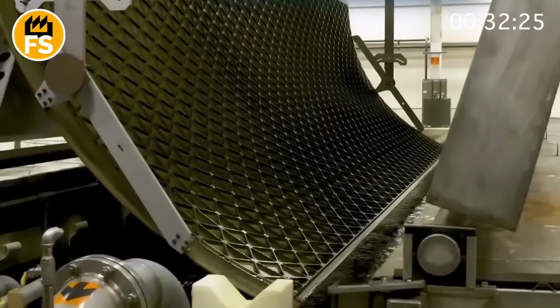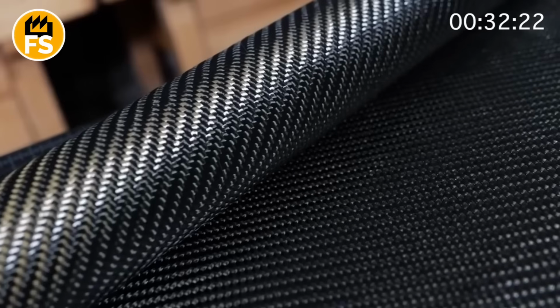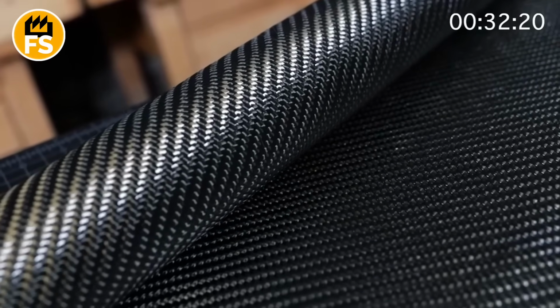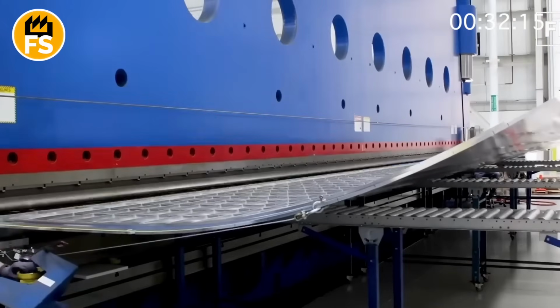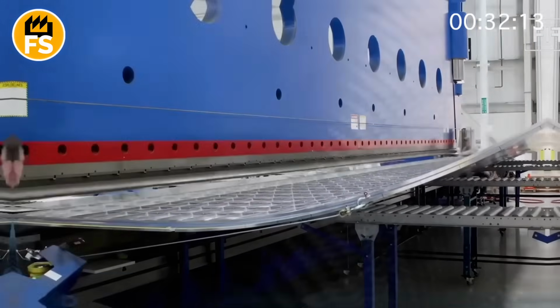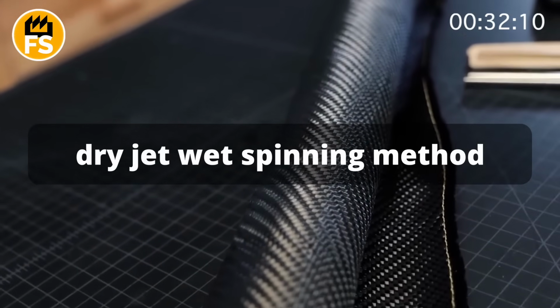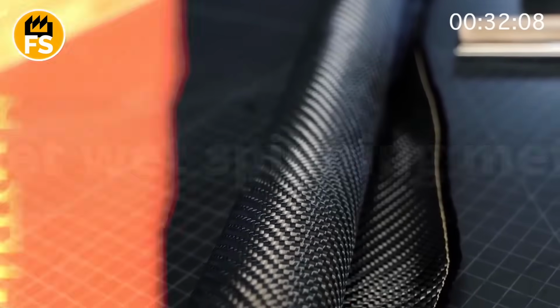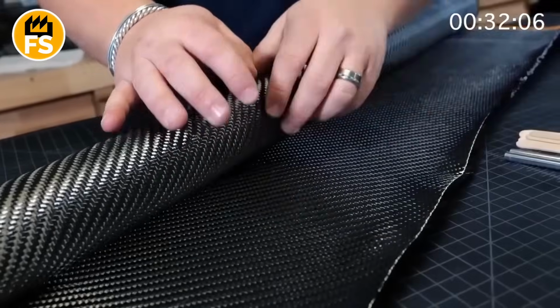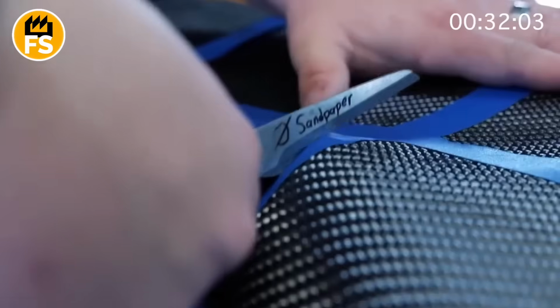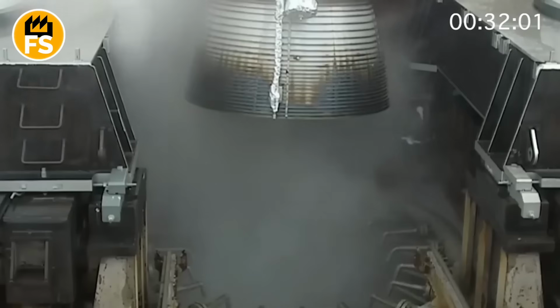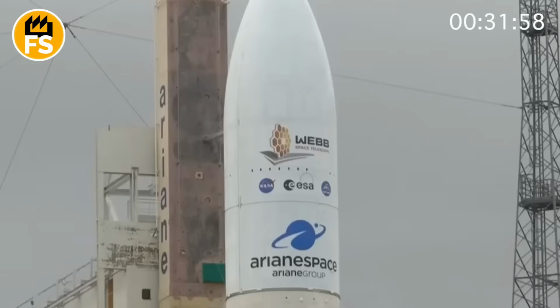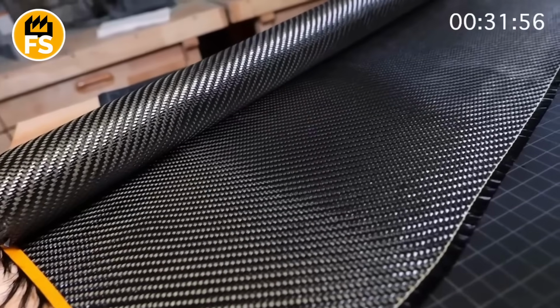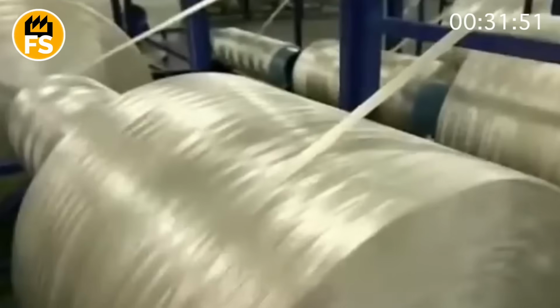Furthermore, research in the field of carbon nanotubes opens up new possibilities for creating fibers with improved mechanical and electrical properties. For example, a team of Chinese scientists developed double-walled carbon nanotube fibers using a dry jet wet spinning method, providing high electrical conductivity, up to 86% of copper's conductivity, tensile strength, and high toughness. These fibers demonstrate durability even after 5,000 bending cycles, making them promising for the aerospace industry and energy storage.